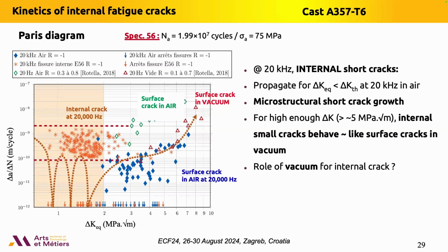And you can see that when the crack is long enough and loaded corresponding to a range of the stress intensity factor approximately higher than 5 megapascal square root meter, the propagation is in very good agreement with the surface crack data obtained in vacuum. These data come from the literature, obtained by Rotella in 2018. If we compare this crack propagation also with the surface crack in air, we can see that the propagation, when the crack is long enough, is in very good agreement with the surface crack in air at 20 kilohertz. So it means that at 20 kilohertz, probably the effect of the environment has not enough time to be applied, and that's why the surface crack propagates in the same way.